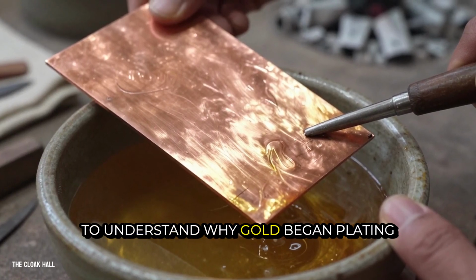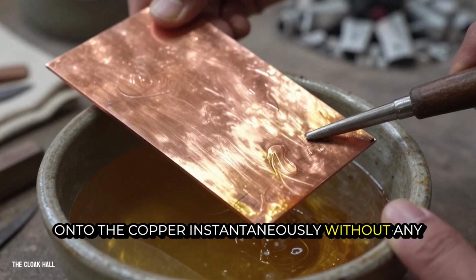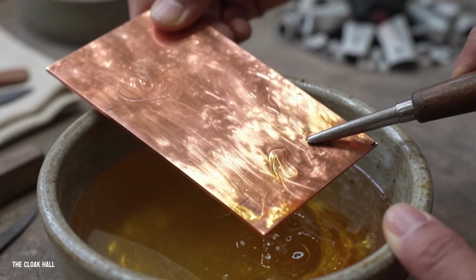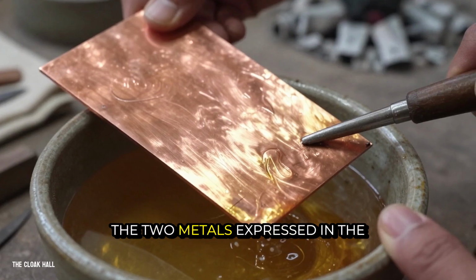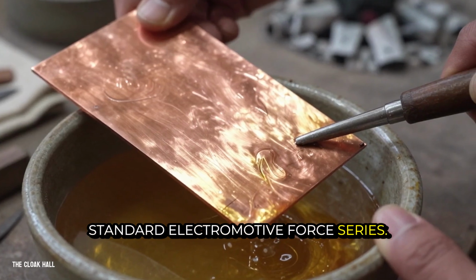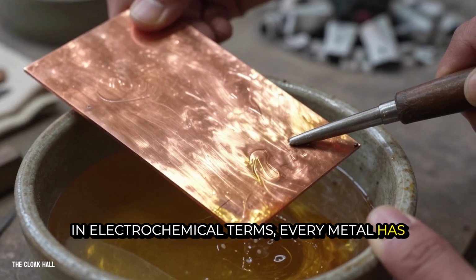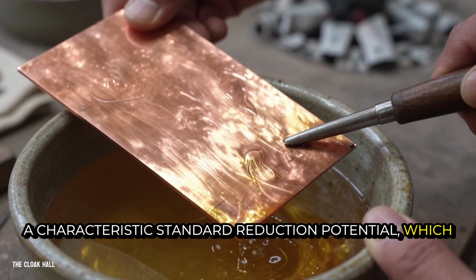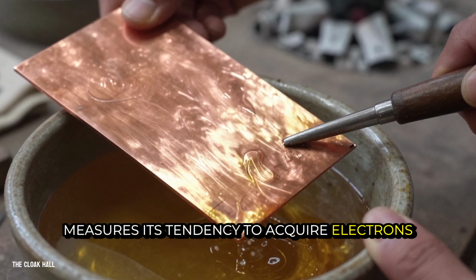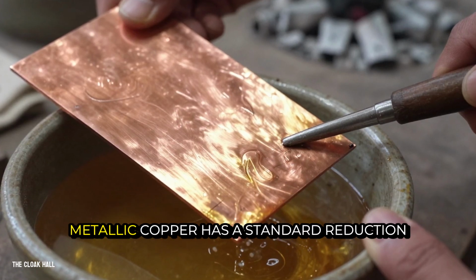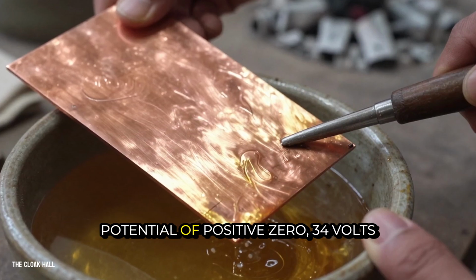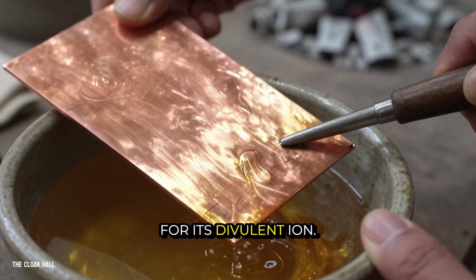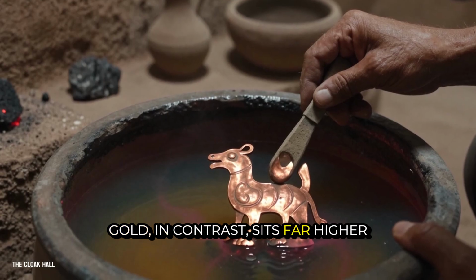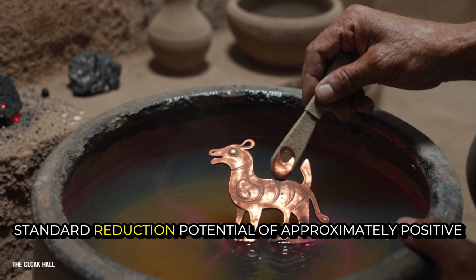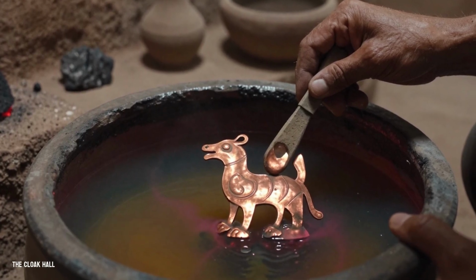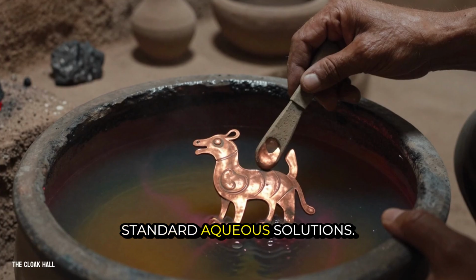To understand why gold began plating onto the copper instantaneously without any external battery, we have to look at the relative chemical reactivity of the two metals expressed in the standard electromotive force series. In electrochemical terms, every metal has a characteristic standard reduction potential, which measures its tendency to acquire electrons and reduce to a metallic state. Metallic copper has a standard reduction potential of positive 0.34 volts for its divalent ion. Gold, in contrast, sits far higher on the nobility scale, with a standard reduction potential of approximately positive 1.50 volts for auric ions in standard aqueous solutions.